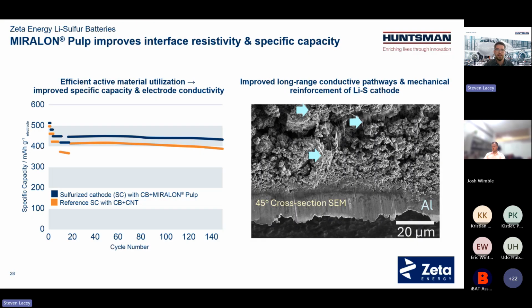So in this slide, you can see on the right with the SEM that the network structure, the CNTs, are bridging between all the active components, which provides a long conductive pathway and also mechanical reinforcement that's needed for lithium sulfur. While on the left, you can see that due to this reinforcement and conductive pathways, you have a higher active material utilization, which improves your capacity. And this also improves the electric conductivity, of course.